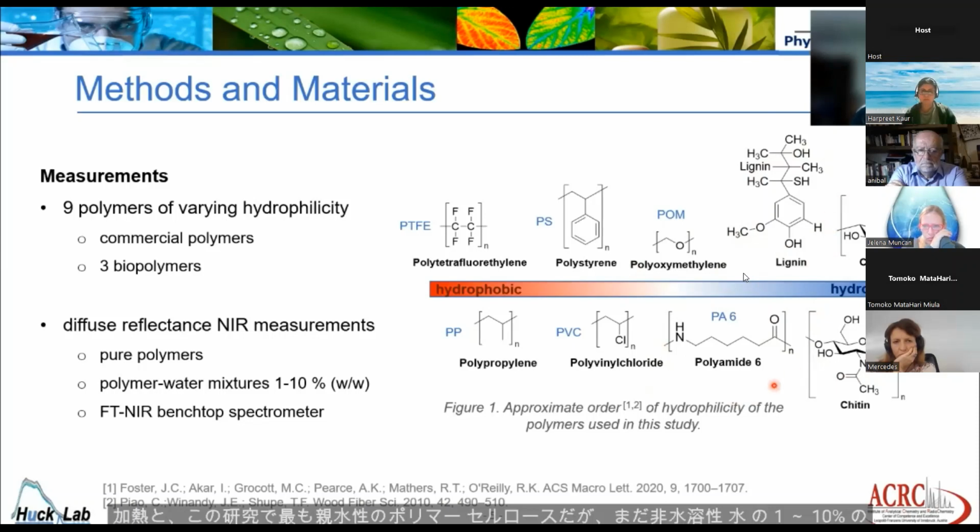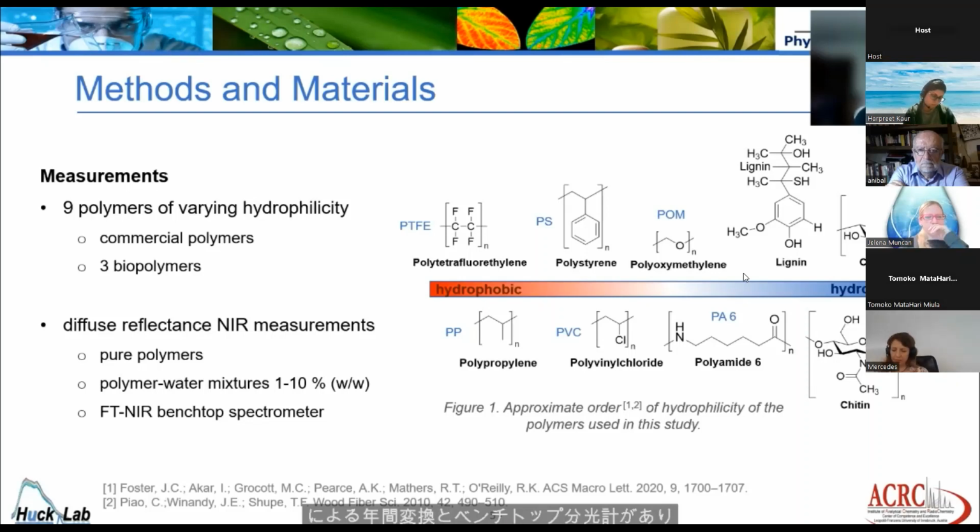non-water soluble. The pure polymers and polymer water mixtures in the concentration range of 1 to 10% of water were investigated by diffuse reflectance NIR measurement with a Fourier transformation NIR benchtop spectrometer.